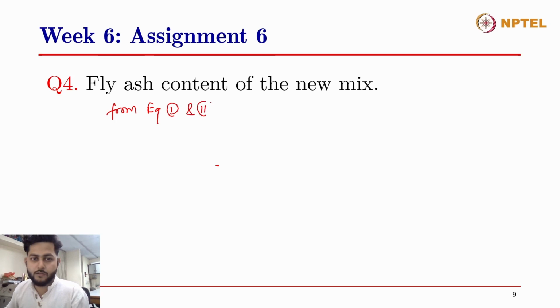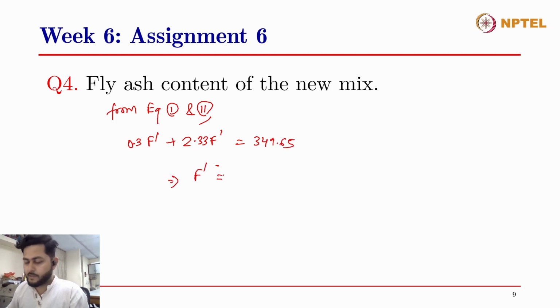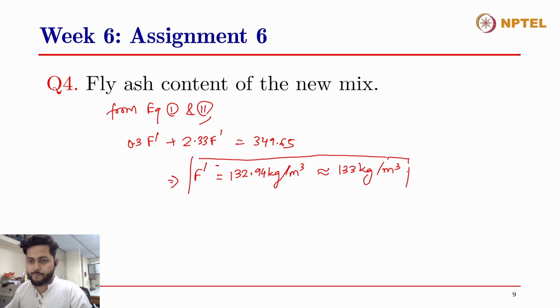Equations 1 and 2, we can calculate as 0.3 F dash plus 2.33 F dash equals 349.65 if we add both of the equations. From that, we can calculate F dash equals 132.94 kgs per meter cube. So we'll just approximate it to 133 kgs per meter cube. So fly ash content is this much in the mix.